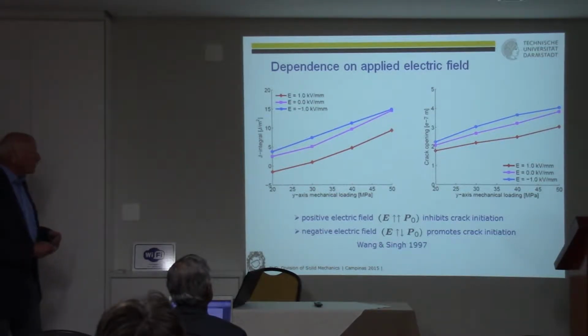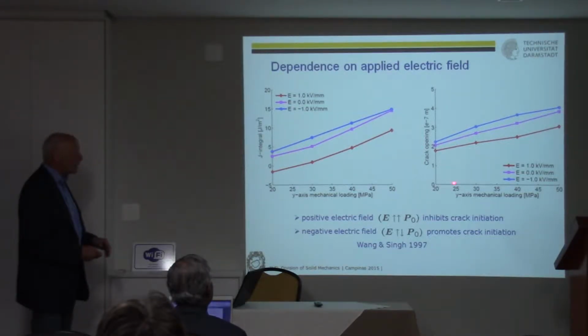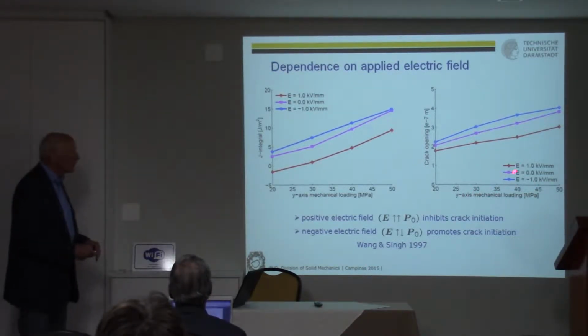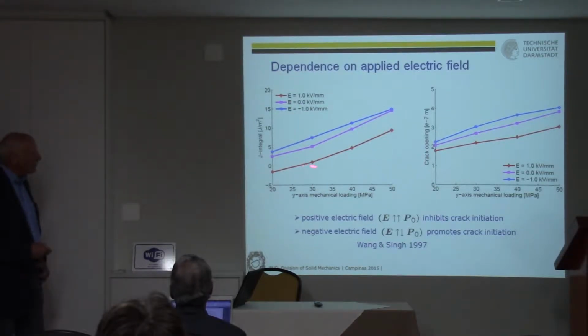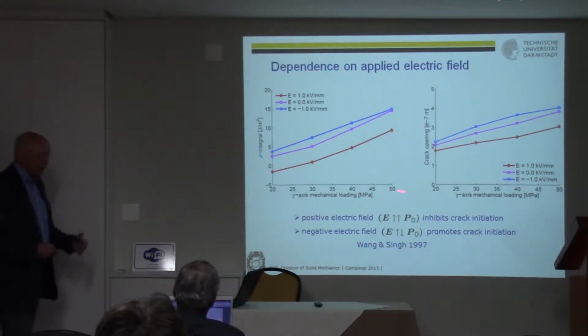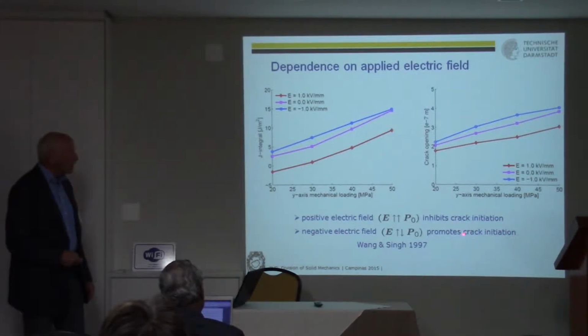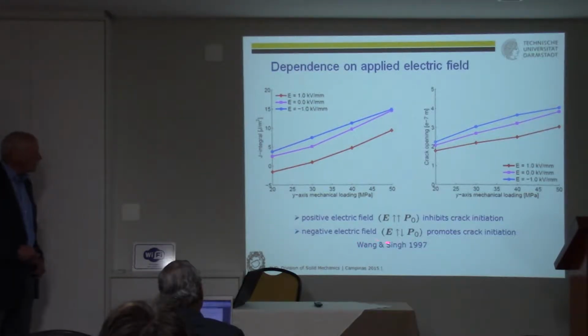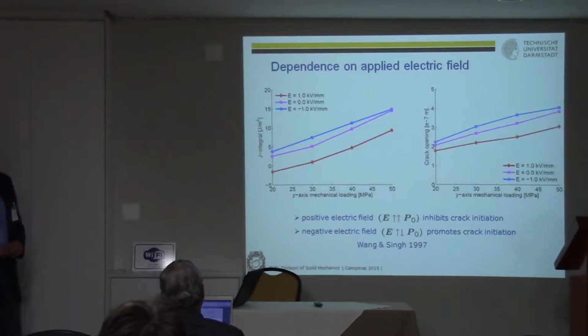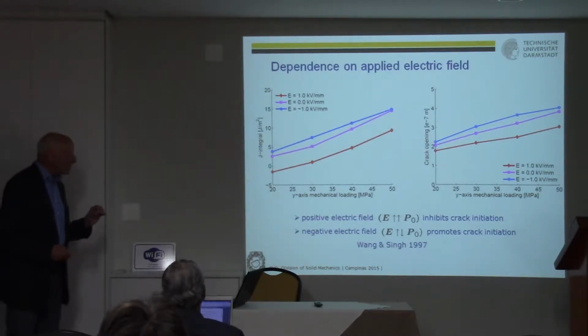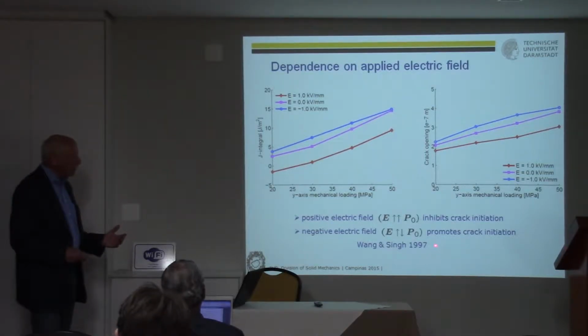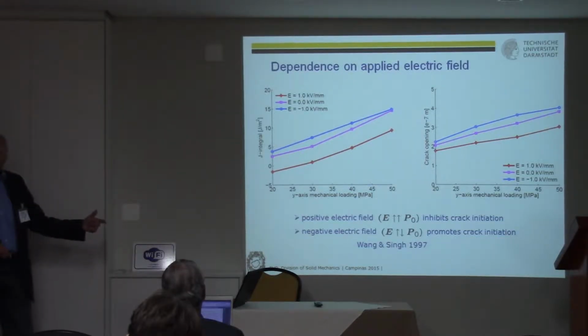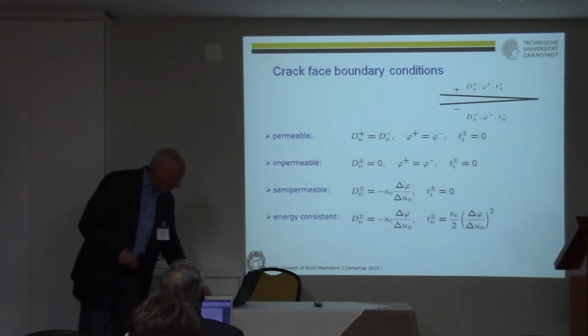And here more or less the same, this is the crack opening versus the mechanical loading for different electrical loadings, and the conclusion you can draw from this figure is that a positive electric field inhibits crack initiation, because you need a much higher mechanical loading to initiate the crack growth. And a negative electric field promotes crack initiation. This is in agreement with experimental results. But I have to mention that the experimental results are not as clear as we would like to have it, because there are other experimental results which say exactly the opposite. But with this, it's an agreement.